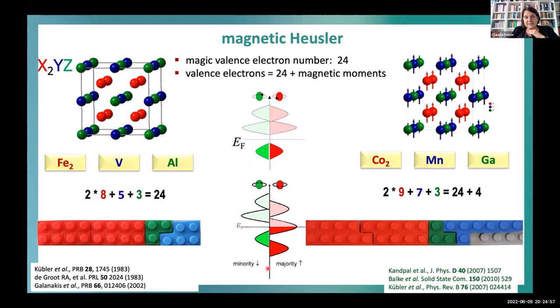So on this side, the green spins are exactly the same as before. They are semiconducting. But now we have the additional spins filled into the red. And so we have a so-called half-metallic ferromagnet. So we have a magnetic moment which is coming from this additional state. So it's exactly the difference between the 24 valence electrons and the additional ones which I put in there. And so we can even predict this. And the